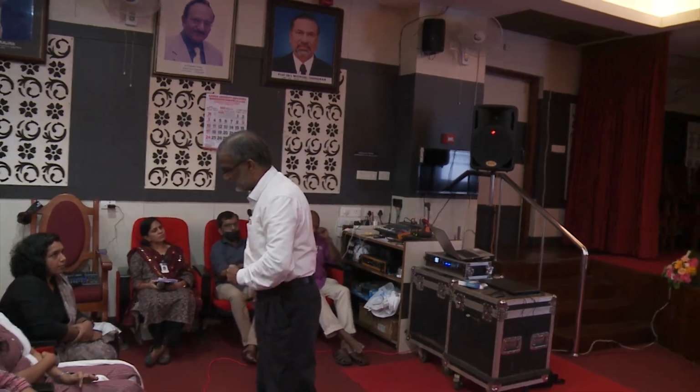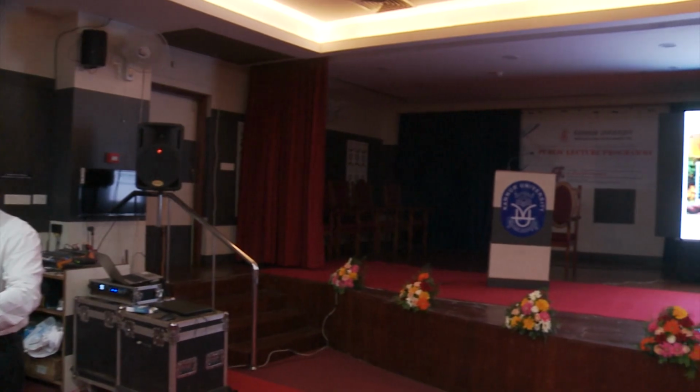How long? With 20 grams of this material, you can run this up to 1,200 liters and arsenic is removed. So, this is to say that in field conditions, in real water, you can create such conditions. So, contaminated water can become clean. So, you can test it in the field.